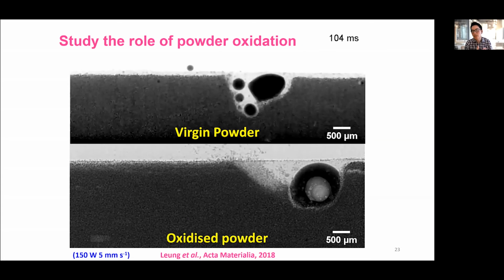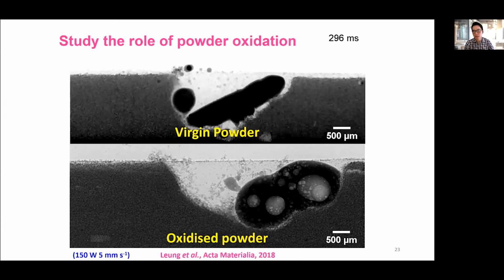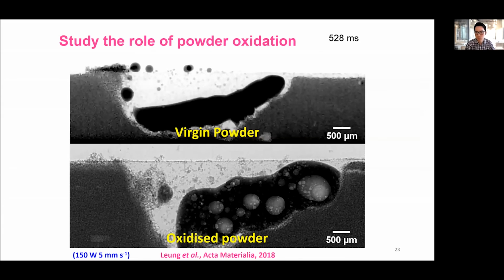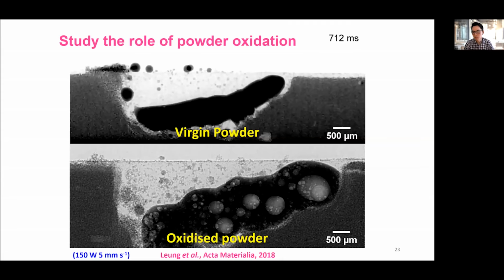So we use this technique and apply that to different types of powders as well. So we're looking at oxidized powder versus virgin powder, because powder quality is absolutely paramount. And you can see with increasing amount of oxygen, it changes the depth of the material. It actually creates more imperfection, and these could be detrimental. So there is actually a growing field in understanding at which point the powder should be recycled, at which point the powder should be scrapped, so that we don't see what you observe at the bottom part of the images.